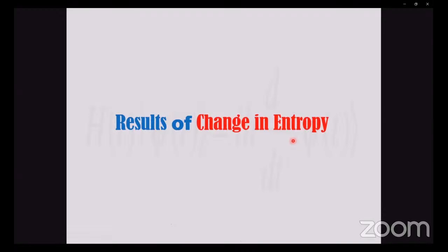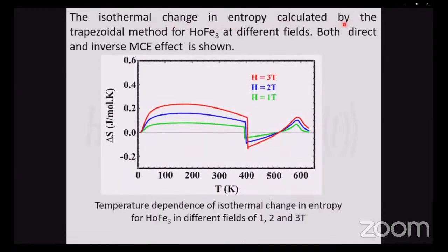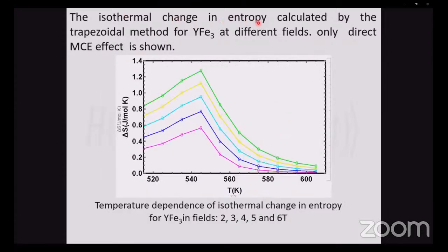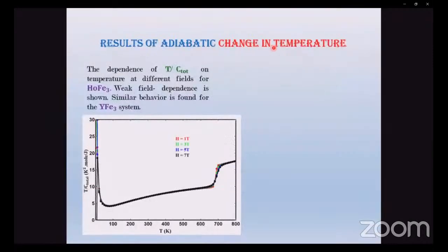The results of change in entropy. The isothermal change in entropy calculated by the trapezoidal method for holmium iron three at different fields: both direct and inverse magnetocaloric effect is shown. The isothermal change in entropy calculated by the trapezoidal method for yttrium iron three at different fields: only a direct magnetocaloric effect is shown. The results of adiabatic change in temperature. The dependence of delta T over C on temperature at different fields for holmium iron three: weak field dependence is shown.